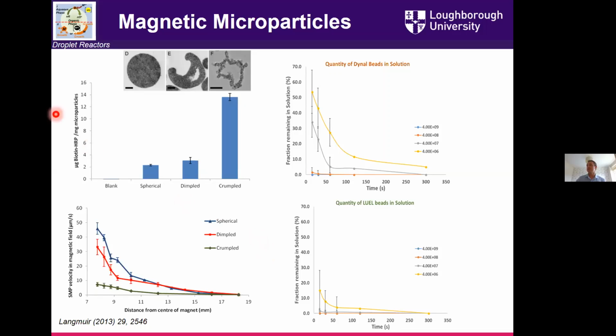And so you can play around with the surface area, you can play around the extraction velocities and how fast they move. But what's important in doing this is also to be able to understand if you're going to add a magnetic particle into solution to extract something, you want to extract all of those magnetic particles. And most of the analytical processes say that you want to do it quick, drop it in, grab hold of the analyte and extract it quickly. And not only do you need to be able to control the surface binding capacity and the speed at which they come out, but you have to have some sort of understanding of how many of these you need to add to solution. Because the number of these particles you add to solution not only affects what you can extract, but also how quickly you can extract it.